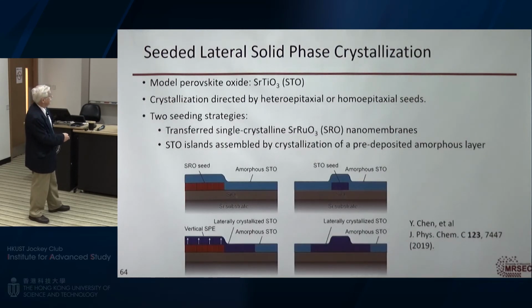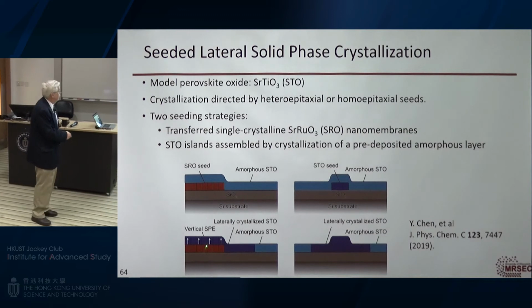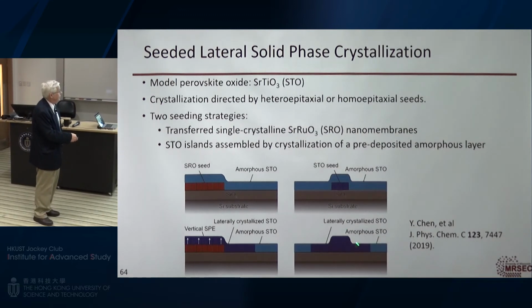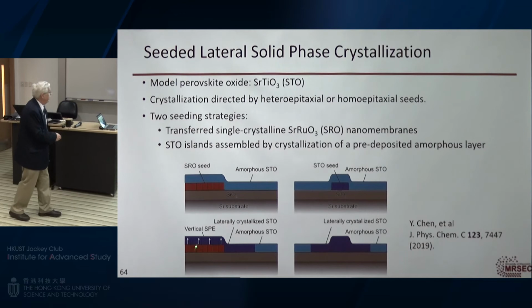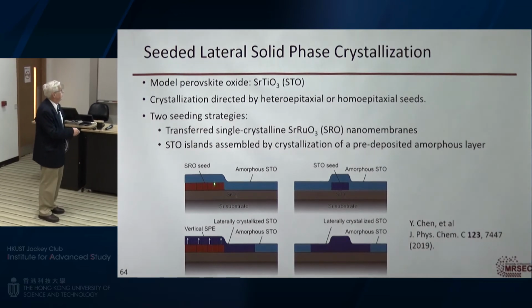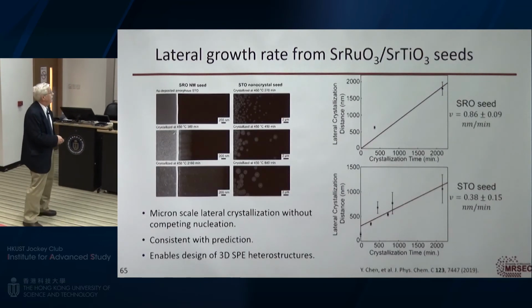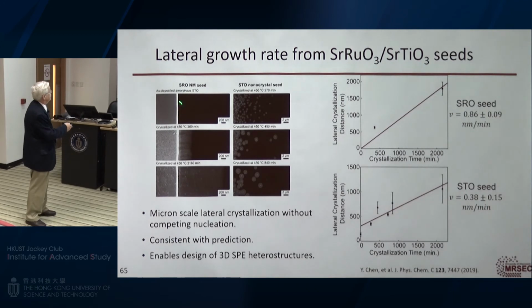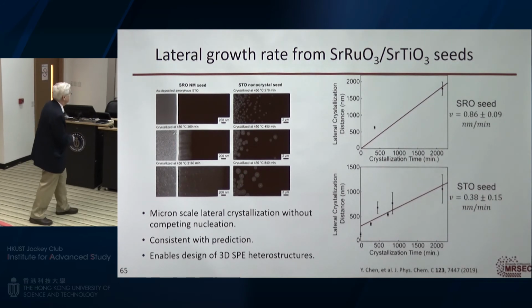And we can do this by seeding it, by putting little seeds down and vertically and laterally growing out from those seeds. And so we can place these seeds anywhere on a substrate, coat it with amorphous material, and form single crystal complex oxides onto an existing substrate. And you can see that we use strontium ruthenate and strontium titanate crystals, and you can see little seeds where the crystal is growing out from there.